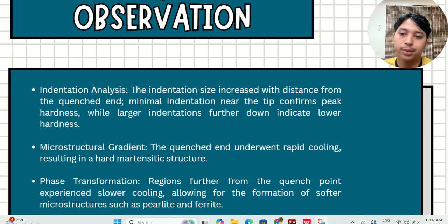Lastly is phase transformation. Regions farther from the quench end cool more slowly, which allows softer microstructures such as pearlite and ferrite to form. The progressive change in microstructure along the specimen illustrates how the cooling rate governs the mechanical properties, creating a distinct gradient from hard martensite to softer phases. That's all from me. Thank you.